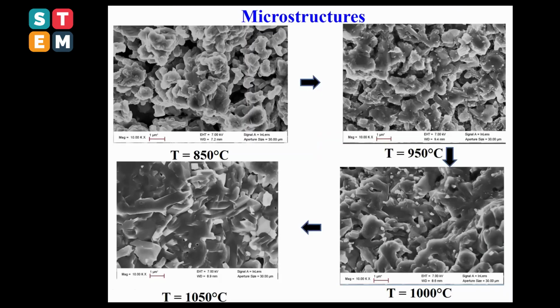Well, when you look at the microstructure of all these samples, this is 850 degrees C. The sample seems to be quite porous. You still have some porosity at 950 degrees C, but the grain size in the sample increases and the sample is more dense when you increase the temperature.